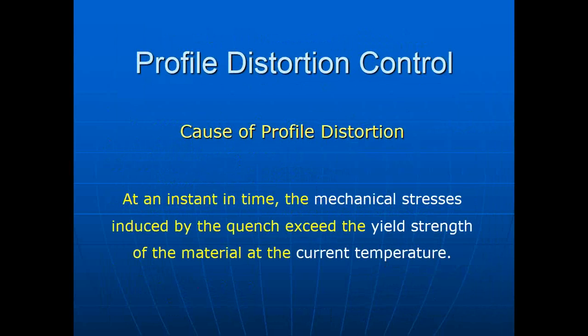When the metal is hot coming out of the press, the yield strength is a couple of orders of magnitude lower than it is after it's been aged and is sent to the customer. So you can look it up in a data book and say, oh, this has 35 KSI yield strength. That's true for a fully processed shape, but you have a tiny fraction of that yield strength when the metal is hot coming out of the die. And this is where we end up facing challenges with geometry.